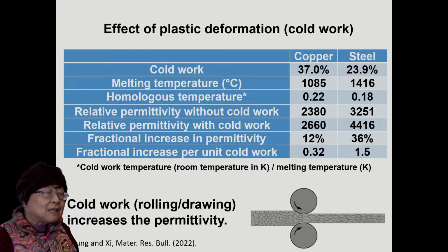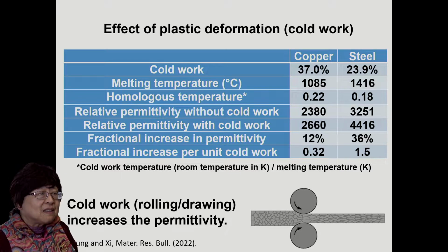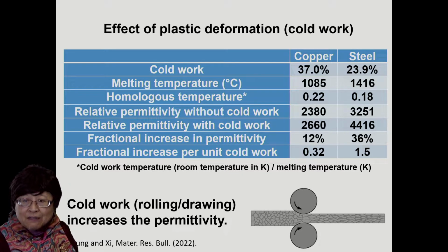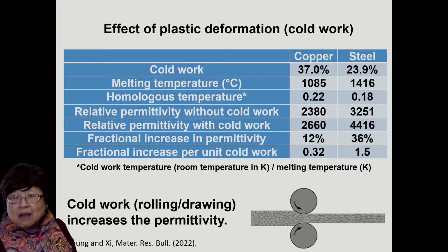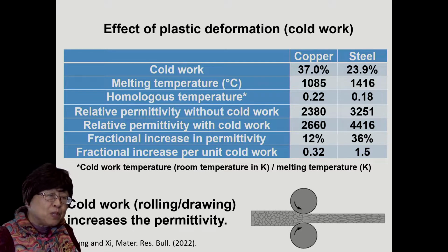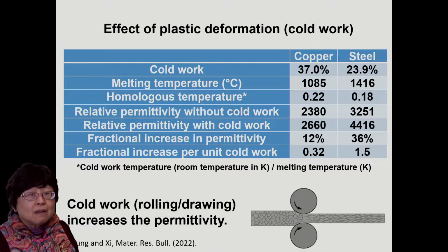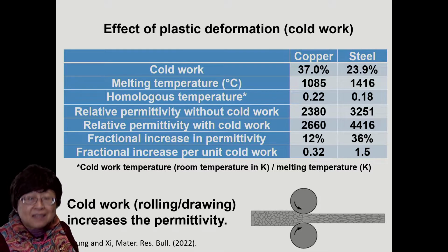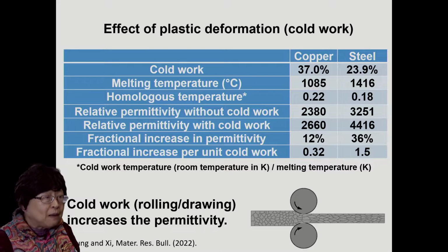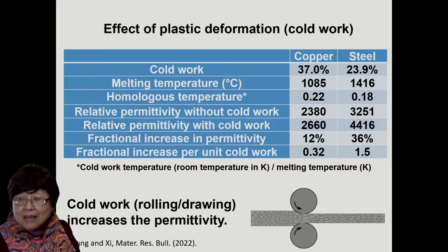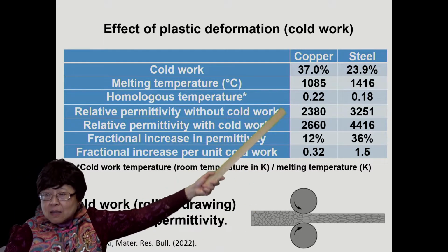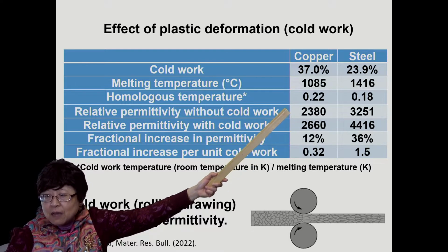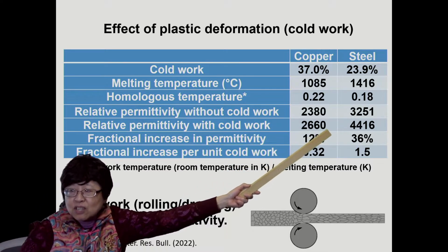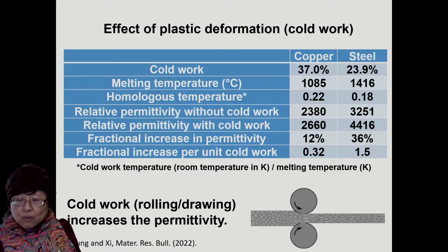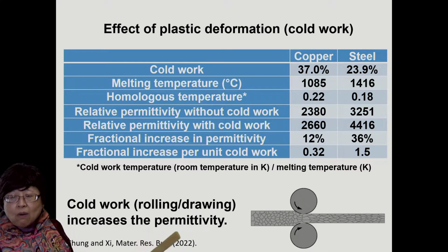Now, not only does grain size refinement enhance the permittivity, cold working also does. We can't cold work carbons, which are too brittle, but we can cold work metals. Cold work means plastic deformation at temperatures below the annealing temperature. And indeed, for both copper and steel, we see that the relative permittivity increases substantially after the cold work in the form of rolling or drawing.